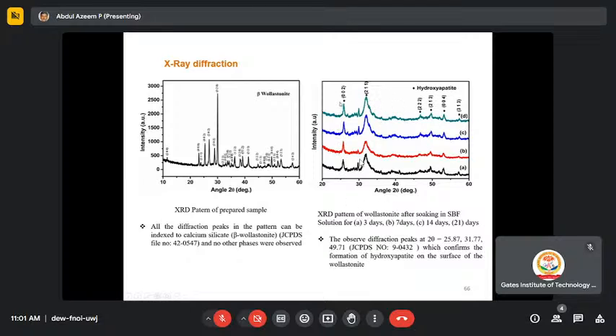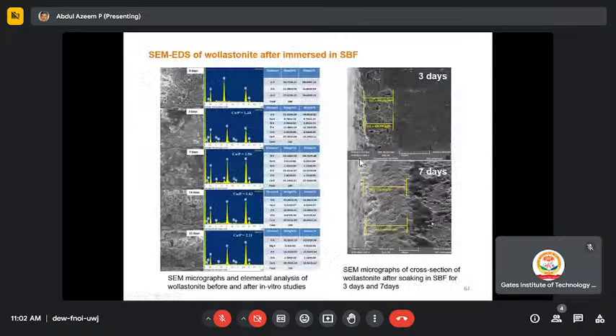We can see that there are crystalline peaks at 002, 211, 222. All these peaks correspond to hydroxyapatite, not the material. So this confirms that there is a leaching of ions between the material and the simulated body fluid. As a result, there is a formation of a layer, which confirms that the material is bioactive in nature. This is what we confirm from XRD.